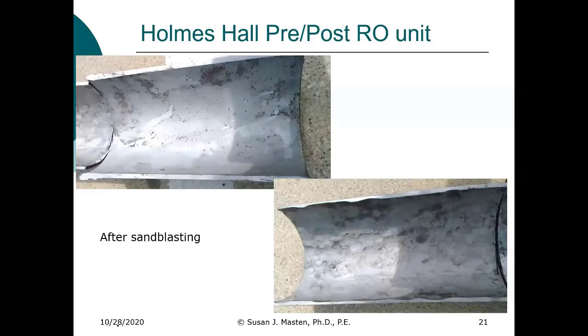These are the pipes after sandblasting, and what I want you to do is look at the thickness of the pipe, and then look at the thickness of the pipe here. So what's happening? I'll answer the red water alert question in a second, but what's happening right here? What do you observe? And what would happen if we allowed this to continue? What's happening is corrosion, and it's actually dissolving the pipe. So if we allow this to continue, eventually, you can see how thin this is here. Eventually, you will have leaks in the system. So the pipe is wearing away.